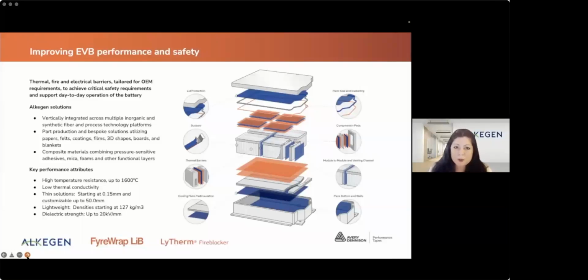Being vertically integrated, we can control the fiber chemistry, product form, and finished piece shape. This allows us to choose the optimal material properties needed for specific applications. As an example, we manufacture fiber chemistries that can resist temperatures up to 1600 C. Materials and finished parts as thin as 0.15 millimeters thick, and pieces up to 50 millimeters thick are available as well. These solutions are extremely lightweight, with density starting at 127 kilograms per cubic meter and have dielectric strengths up to 20 kilovolts per millimeter.